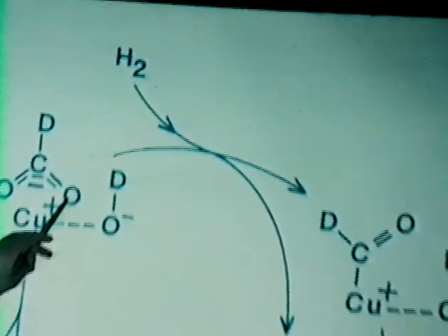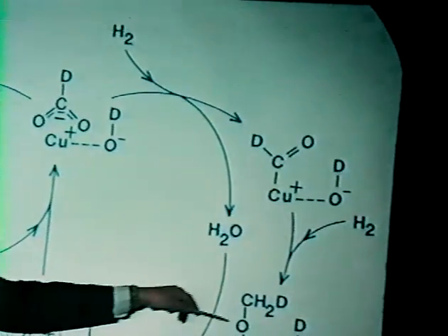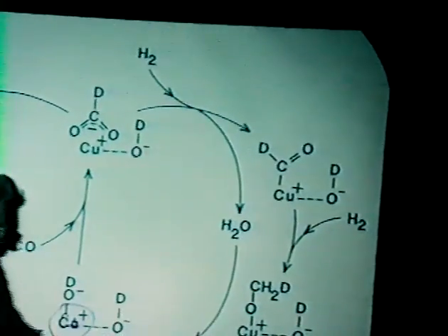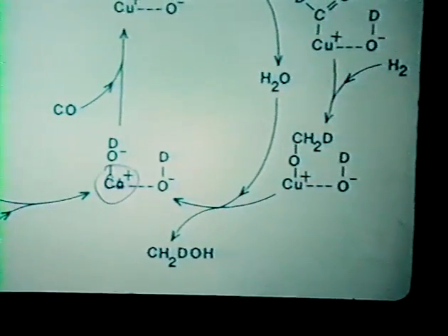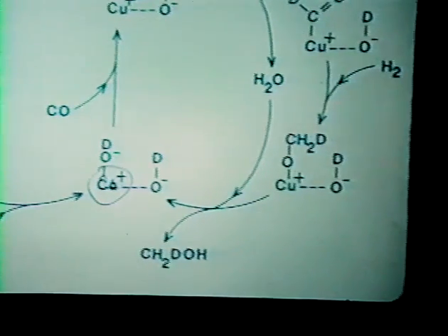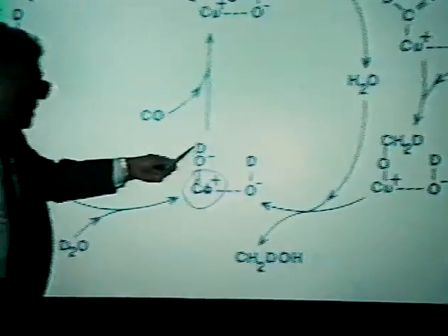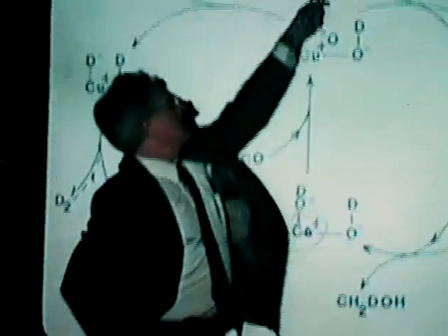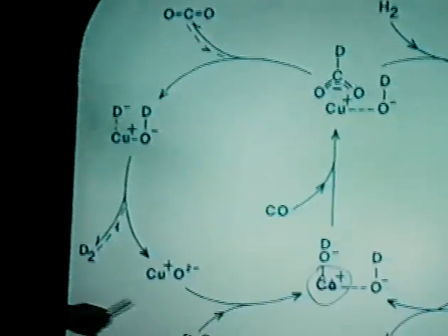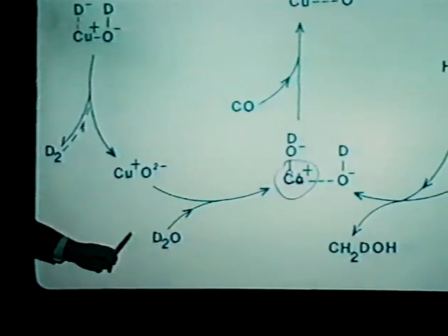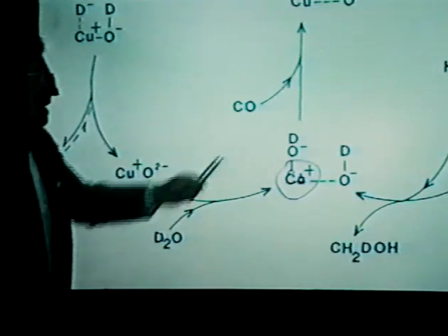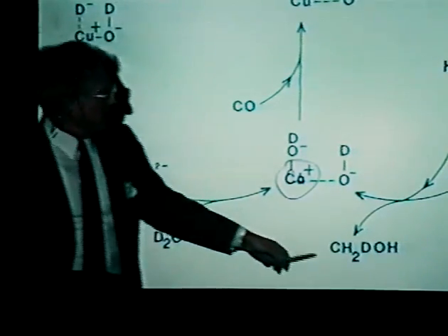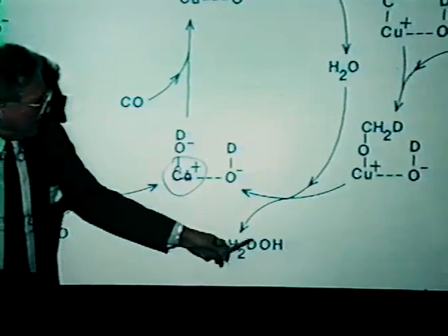Then this gets reduced and rejects one of the two oxygens in the form of water, gets reduced to surface methoxide, then the surface methoxide gets hydrolyzed to methanol. What is shown here is a result of isotope work in which we were putting in the deuterium not from the gaseous hydrogen, which is the hydrogenating agent, but from the D2O, which is a major promoter for the methanol synthesis, forming the OD groups, and one of the three atoms of the CH3 group ended up as deuterium.